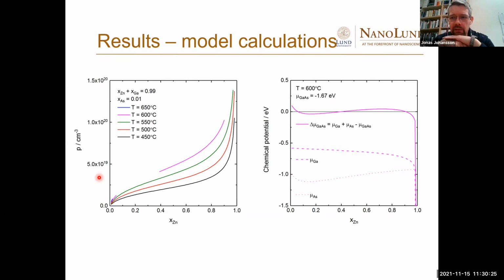In general, I think it could. But in aerotaxy, I'm not so sure, because the growth is completely saturated. We have such high pressures that if we change the pressures a little bit, it will not make a big difference. And with such high precursor flows, I don't think we could come to a more nucleation limited situation. But in other systems, I think there could be a chance, in MBE or MOVPE growth at lower pressures. Yeah, why not?